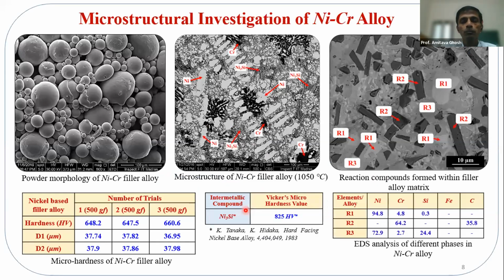So as I said, there is a lot of metallurgy involved in it. We need to see how this filler material behaves when it is intended to join the diamond to the substrate. So it is taken in the powder form. Each globule, you can see, is basically a powder metallurgy product, produced through the powder metallurgy route. When we melt it and analyze the microstructure, we can see nickel matrix solid solutions, some with chromium, but in the matrix of the nickel, there are some nickel silicides which get formed.